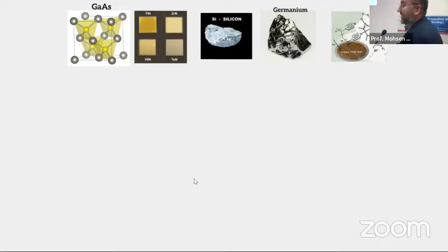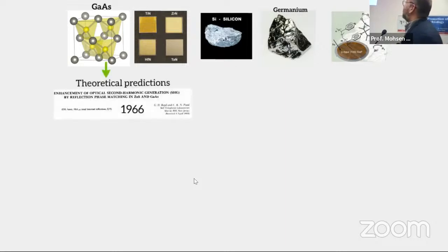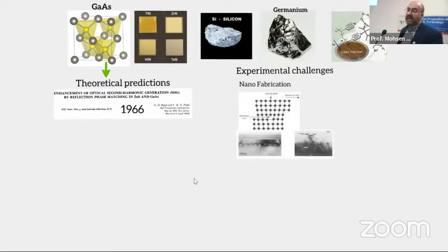These III-V semiconductors are actually the best material in terms of nonlinear properties, or nonlinear susceptibilities. But it was not a secret. From 1966, it was known that these materials have the highest susceptibility, but because of the problem of growing them and the lattice mismatch of these III-V semiconductors, it has been a problem. So then we needed to find a way to grow them on the substrate which we want, like glass, quartz, and low refractive index substrates, magnesium fluoride, and so on.